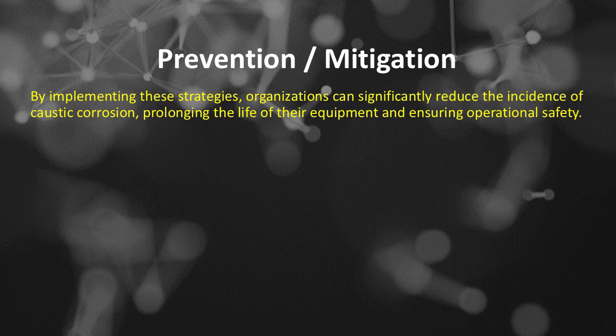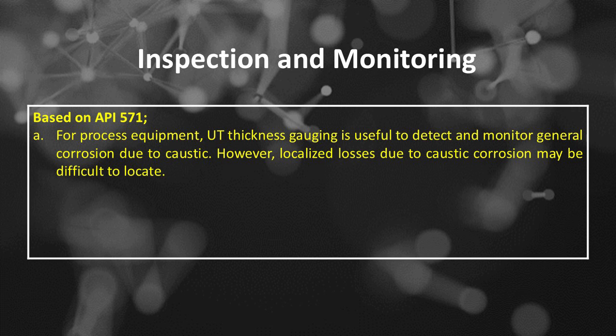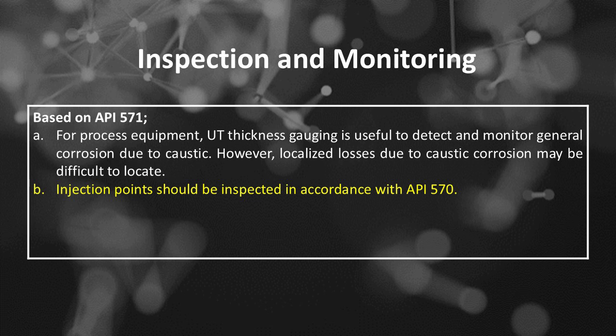ensuring operational safety. Caustic corrosion inspection and monitoring based on API 571, Number A. For process equipment, UT thickness gauging is useful to detect and monitor general corrosion due to caustic. However, localized losses due to caustic corrosion may be difficult to locate. Number B. Injection points should be inspected in accordance with API 570. Number C.